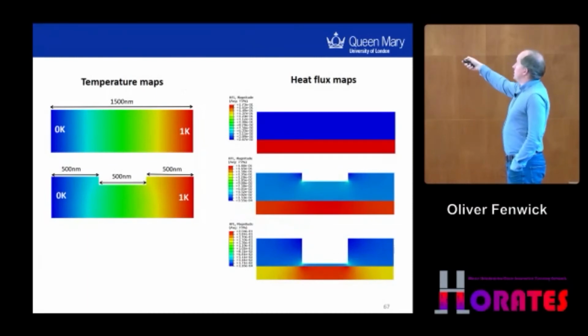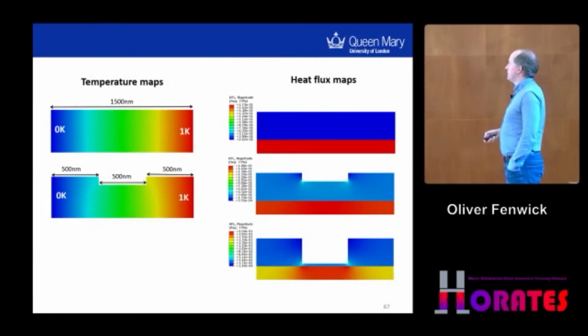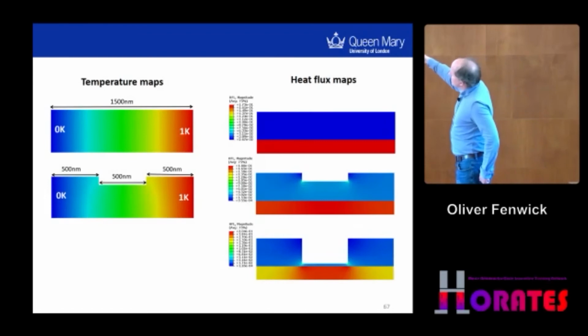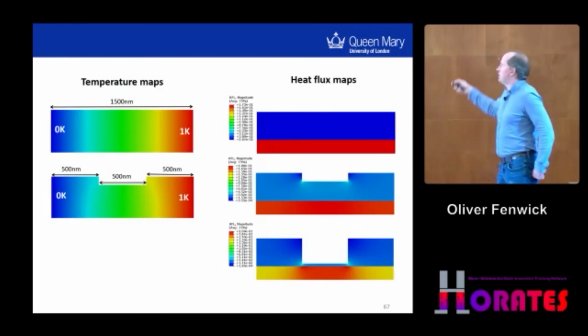You can look at this in different ways. On the left, we've got the system when you have no indentation. This isn't really 0 Kelvin, it's just a fixed temperature and then 1 degree hotter on this side. And you see that the temperature varies linearly from one side to the other. It's also, of course, the same in the membrane as in the material because they're in thermal contact. If you put an indentation here, it looks fairly similar, but you can see there's some slight distortion to the temperature map around the indentation.